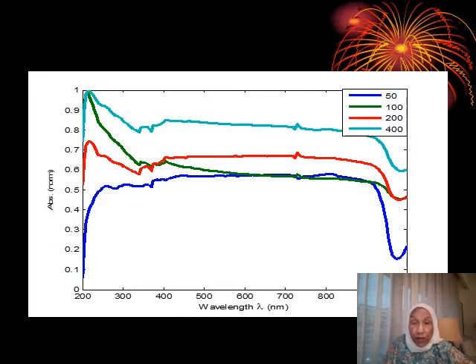Then we made optical absorption to see whether the range of solar spectrum will affect the absorption and will be absorbed into these different samples. And we found that as the sample size increased, from 50 to 400, the optical absorption increased from 0.56 on average in the range from 400 to 800, up to 0.8, that is increased in all the region.